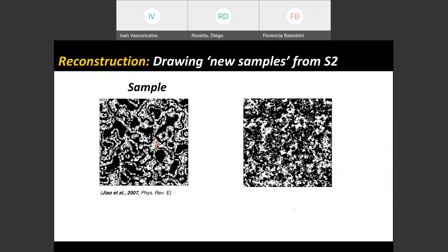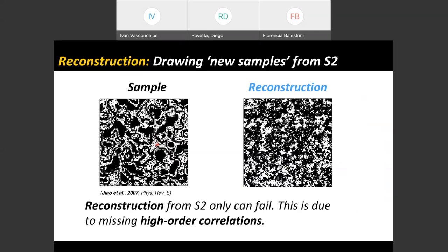Now, if we sample the two-point correlation function and then reconstruct it, we get this reconstruction. And you can see that this fails dramatically. This looks nothing like the sample. The reason this fails is that this material has high order statistical correlations, and S2, or the two-point correlation function, is too low order for this material.